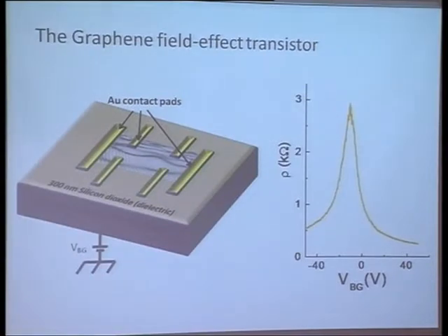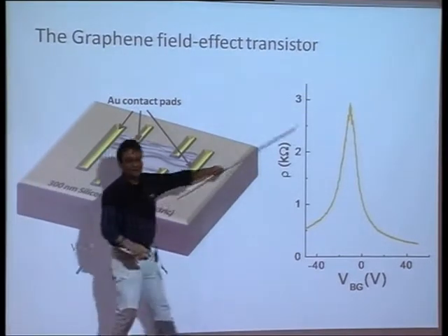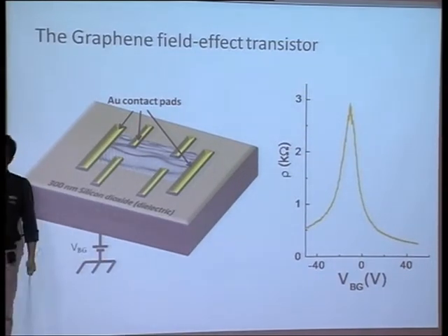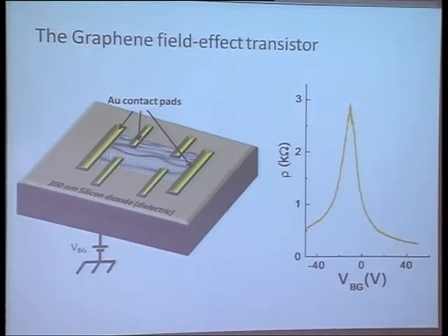I'm actually very happy that you noticed it. You never get that peak at zero, because when you create this graphene, you dope the graphene immediately. There is a transfer of charge between the oxide and the graphene, which shifts the charge neutrality point slightly. Using the gate voltage, you essentially change the carrier density. The importance of this will become imminent very soon, because these transferred charges are the major source of momentum relaxation. They get trapped in the substrate, apply a Coulomb potential back on graphene, and the electrons in graphene get scattered by them.